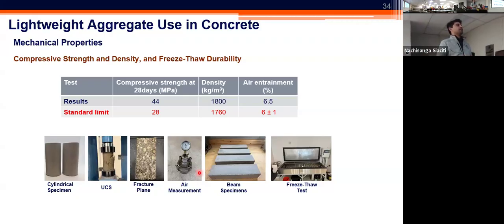So we did this type of testing, and to our surprise, the value of the reduction was only about 10%. So we retained 90% of the original dynamic modulus, and therefore considered the tailing-based aggregates as successful. And to our surprise, the control samples that we made from commercially available lightweight aggregate all failed and crumbled by the end of the test. So we even had some bragging that tailing-based aggregates were superior to those commercially produced lightweight aggregates that you could buy from some of the nearby facilities. So that's essentially the evaluation of the aggregate, but obviously more work needs to be done so this can be adopted at a larger scale.